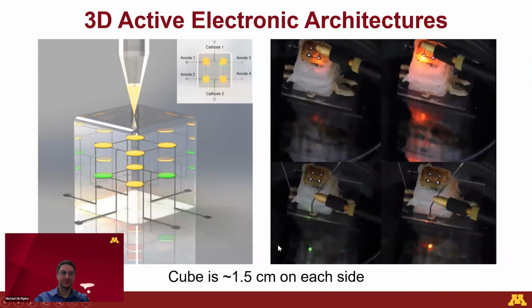And the real cube doesn't look quite as beautiful as the drawing on the left, but it looks okay. And so what you can see here is that there's silicone that we 3D printed, and then you can see these blobs of the liquid metal on the top there. And then you have the quantum dots in there. You have these electrodes, which are also 3D printed, coming out the side. This entire structure here is 3D printed. And as you probe different regions of the cube, you can see you have either orange emission or green emission from the cube, depending on where you're probing it. So this is a truly three-dimensional active electronic architecture, and the cube is 1.5 centimeters on the side. So it's a macro scale object, but the printing can be done down to the micro scale, and then the quantum dots are nanoscale. So the cube itself is sort of multi-scale and multifunctional, embedded within this object here.